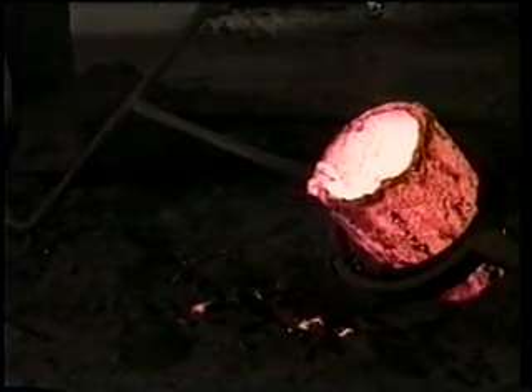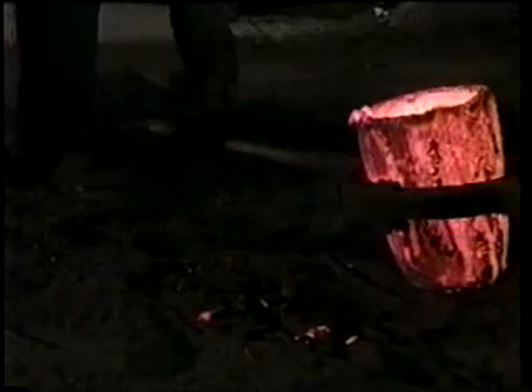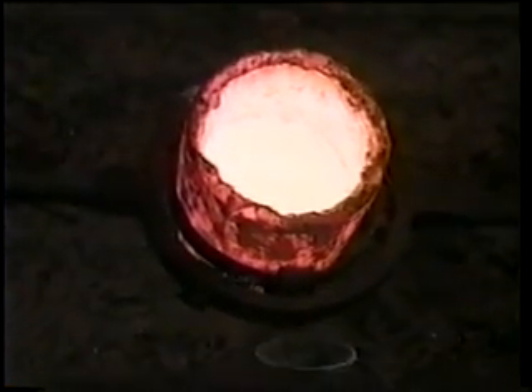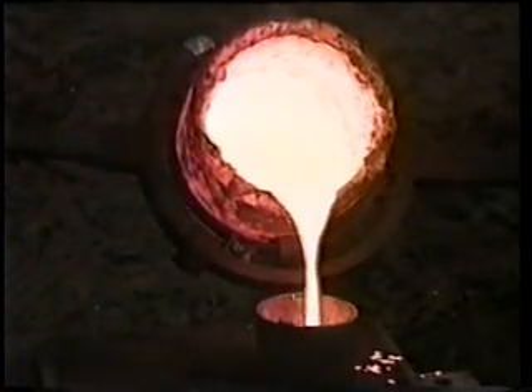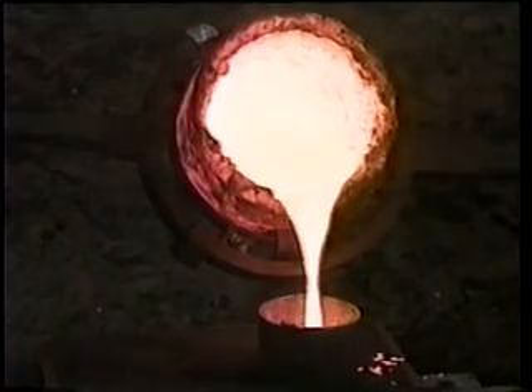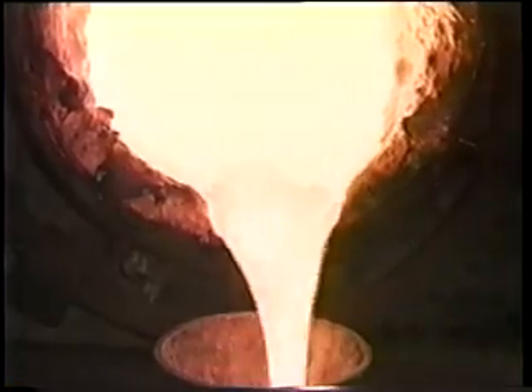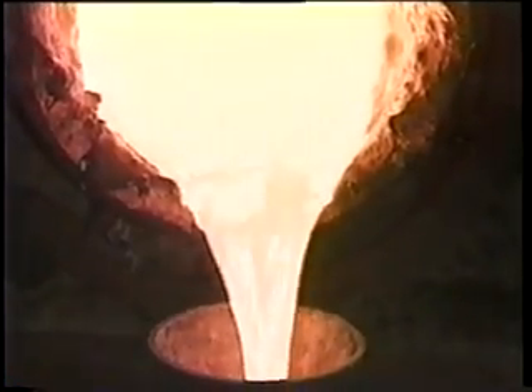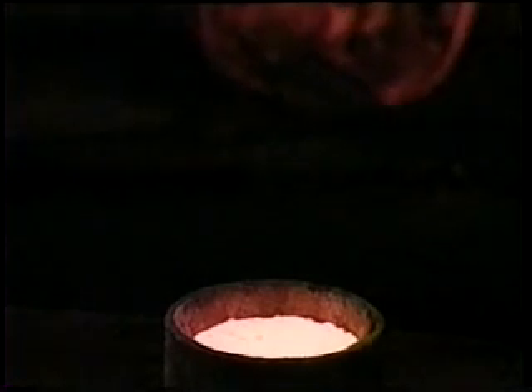Also, our modern plumbago crucible will withstand much higher temperatures than those used in prehistory, allowing more time for pouring the molten metal into the moulds. For a mass of about 200 grams of molten copper, about enough for one axe head, prehistoric smiths would have had only about 10 to 15 seconds to perform the entire pouring procedure before the copper started to solidify.